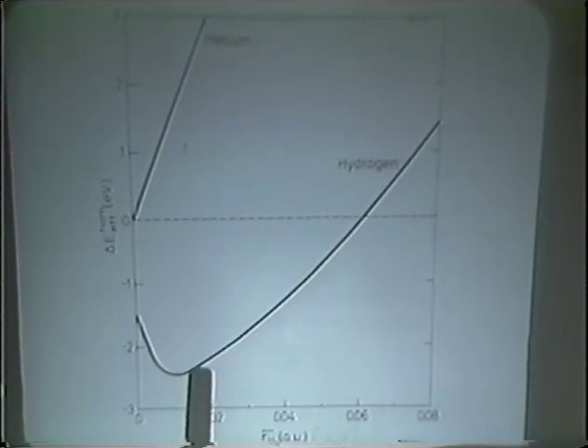But the next hydrogen you put in the vacancy is lying on the opposite side here, so there will be little interaction between these 2 hydrogen atoms. But then when you start to fill the other hydrogens, there will be a hydrogen-hydrogen interaction, which then gives rise to a decrease in the binding energy here. But that's again easy to understand within this scheme here, because what matters is that the other hydrogen is donating electron density to the certain hydrogen you're looking at. And that means that you move from the minimum up here along this curve, and then your gain in energy, the trap strength here, is decreased. So you see that the trap strength of the last hydrogen in the vacancy is lower than that for a single hydrogen in a vacancy.